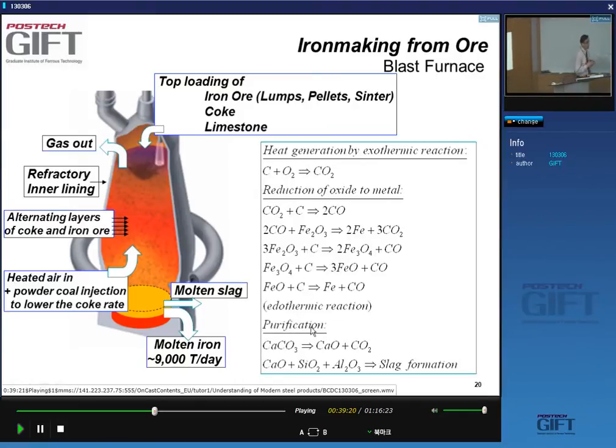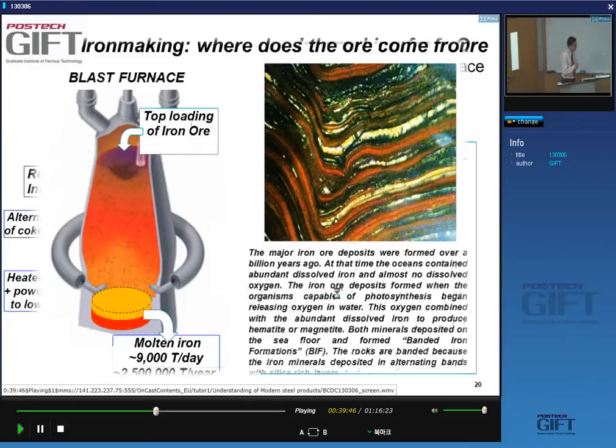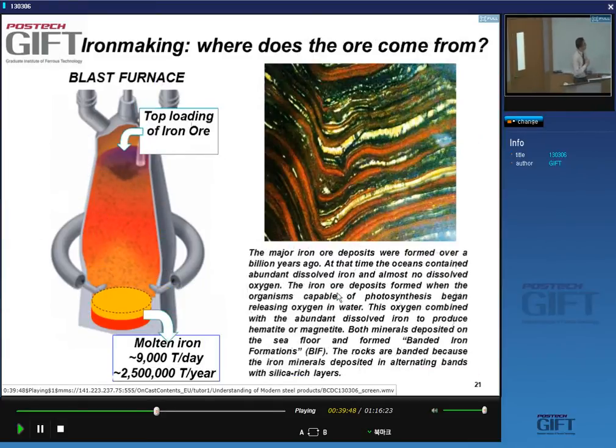The other very important thing that happens is purification. That's why we need the limestone in this blast furnace, because the limestone, which is calcium carbonate, will create calcium oxide, which will form together with the impurities SiO2 and Al2O3 this liquid slag.